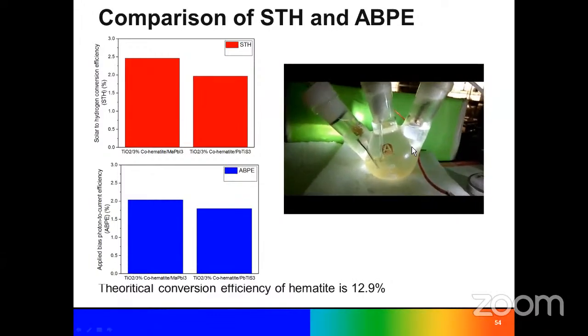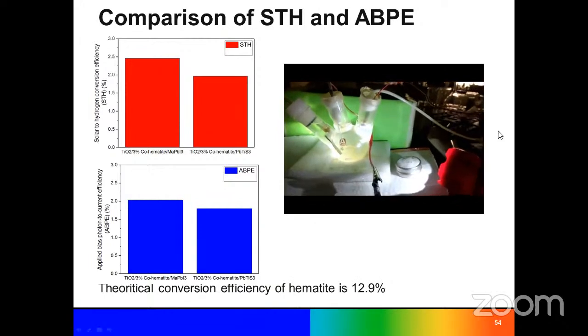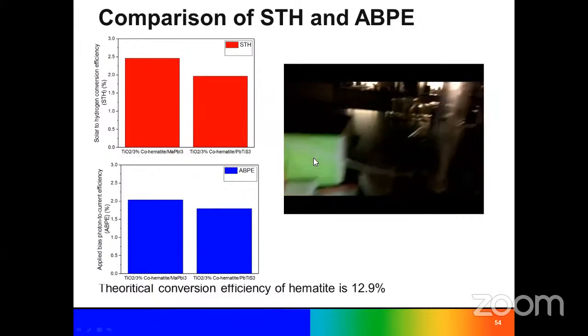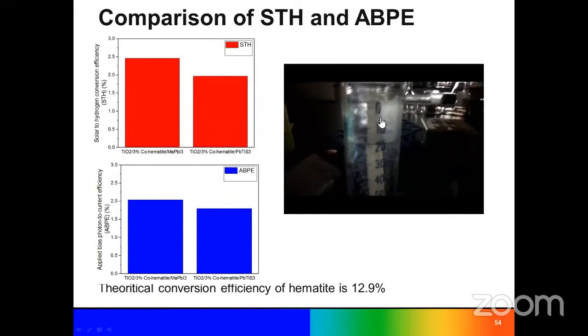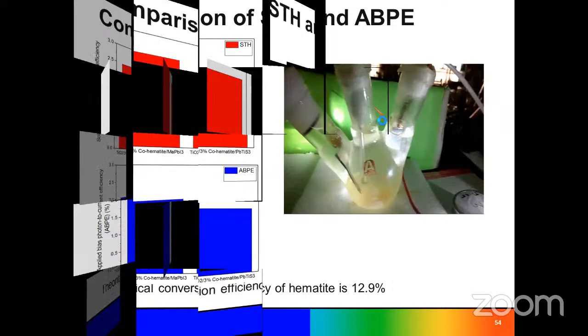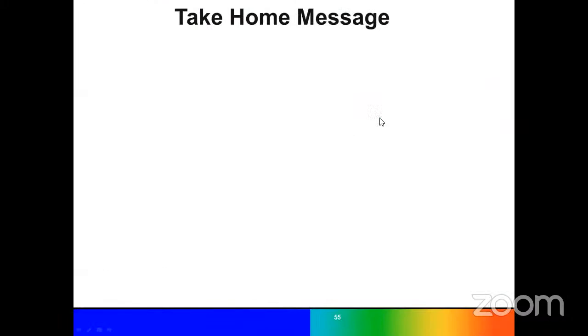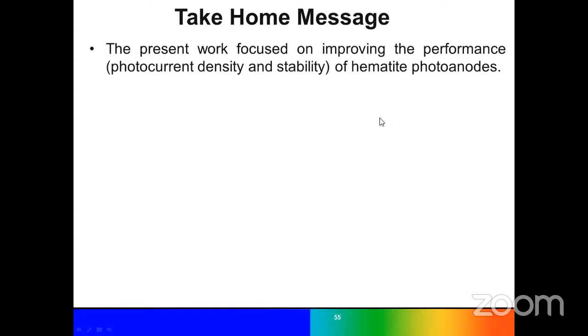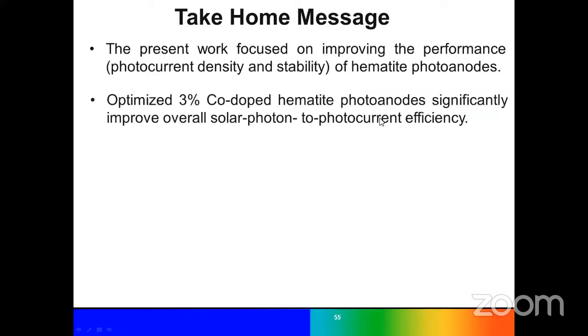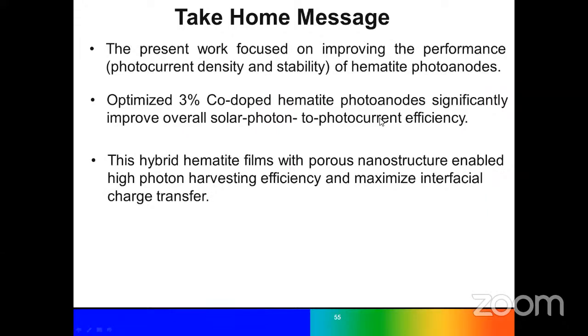So if you see this video, in the presence of light, the photoanode produces hydrogen, and we store this hydrogen in another section. This is the counter electrode, the platinum electrode, and here we measure the amount of hydrogen stored in this section, how much hydrogen we store in how long a time, using only this light. So this is our attempt at water splitting device fabrication with hematite, using doping and structural tuning to get the maximum solar to hydrogen efficiency and photon absorption efficiency. Still, some challenges are there.